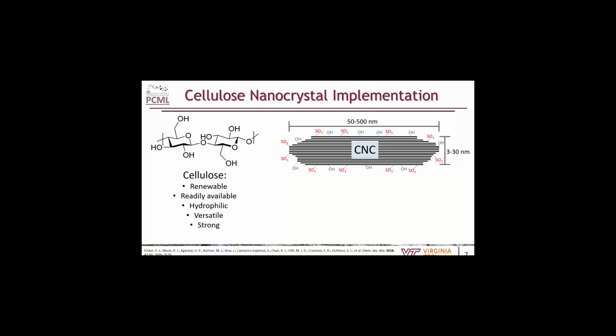And in the materials we're using, which are derived from wood pulp—hardwood, trees, etc.—they're about 50 to 500 nanometers long and can be anywhere from 3 to 30 nanometers tall or wide. They're shaped like a cylinder or a spindle, really, because each of those layers just twists a little bit, kind of like a DNA helix.